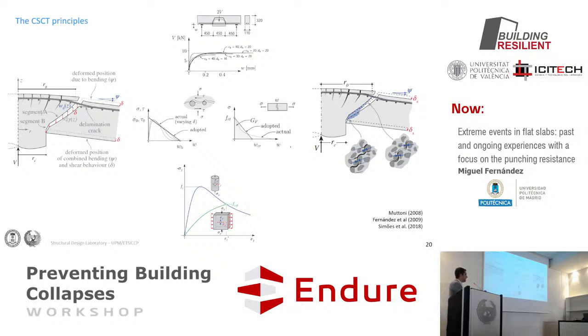So with the kinematics and some constitutive laws, it's simple. You can integrate all of them, and then you get the state of stresses. So you're getting a stress field which is based on the kinematics that we assume and some constitutive laws. And here you see a calculation of where the intensity is, where the force is being transferred. So a large part is transferred on the bottom, but also through the crack there is something being transferred. So this is the way the critical shear crack theory works.